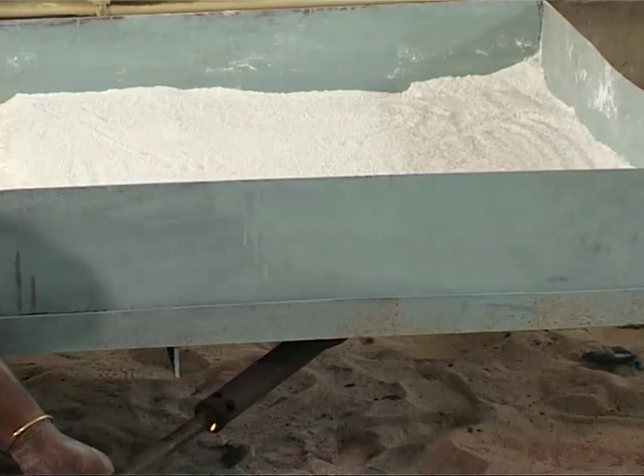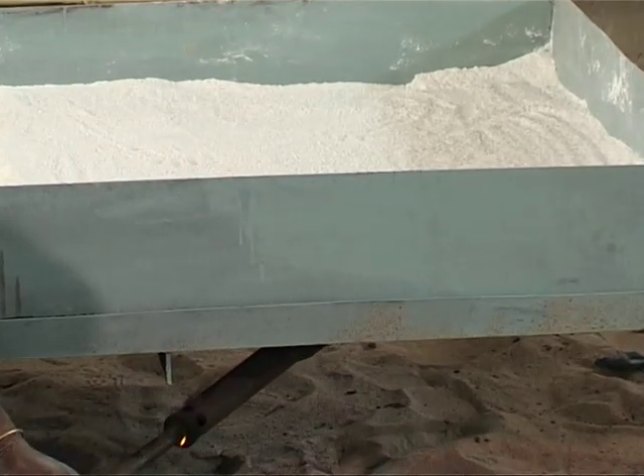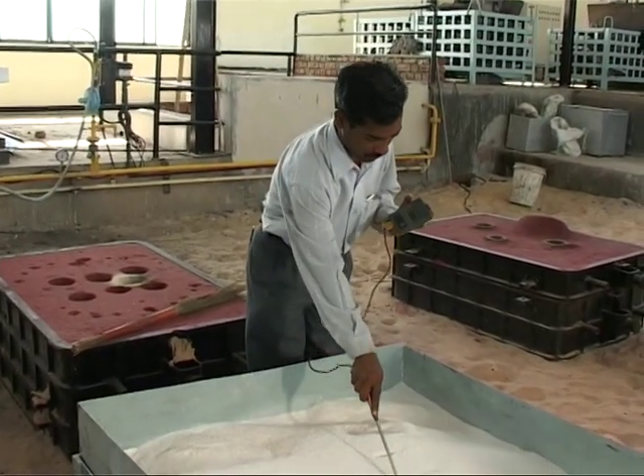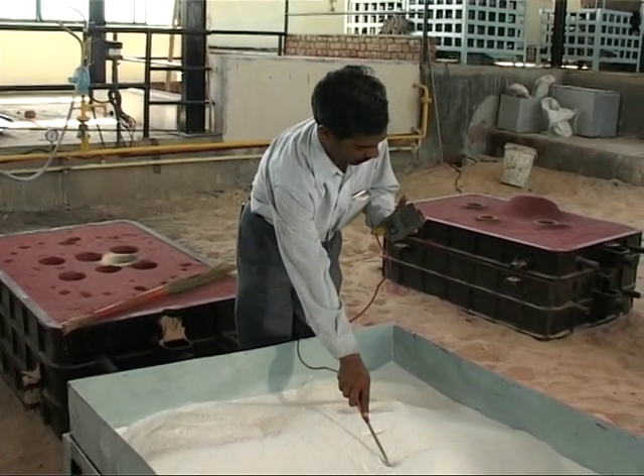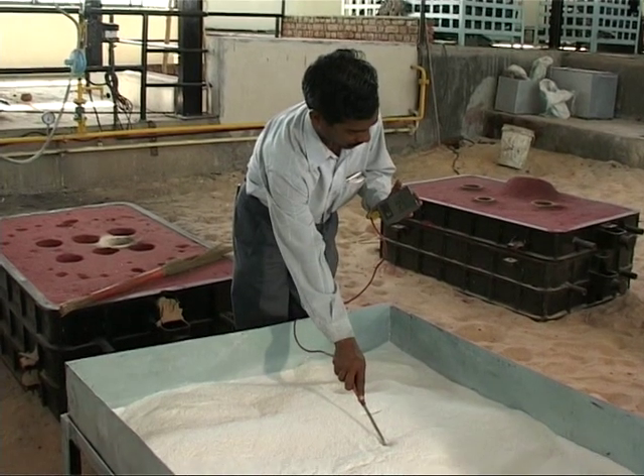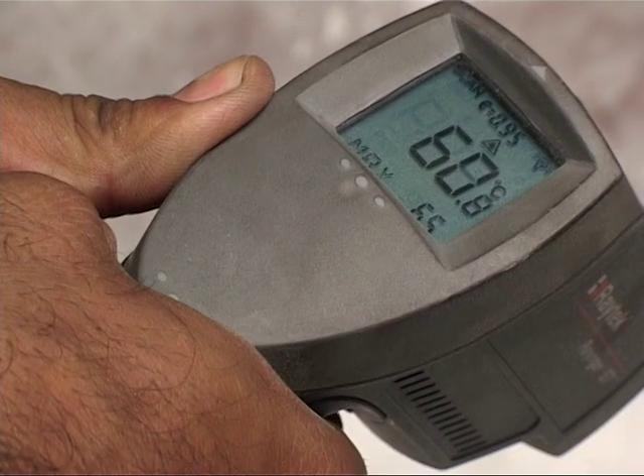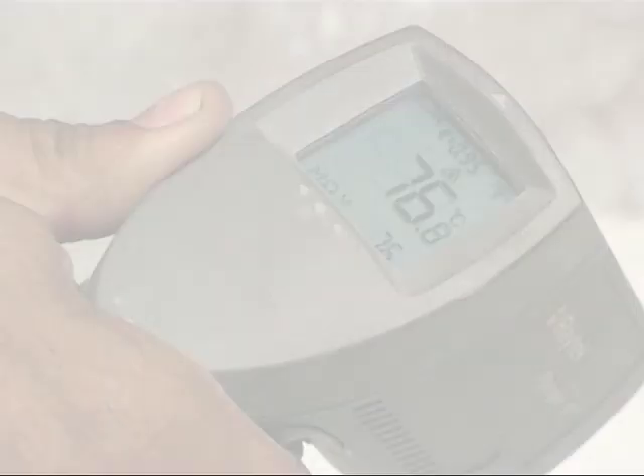Demagnetize and heat a second batch while the first is cooling. Boric acid loses its first molecule of water at 80 degrees centigrade. If boric acid is added while the ramming mass is too hot, it will melt to form globules and cannot be distributed uniformly. This may allow pinhole-like defects to be seen in the lining surface.